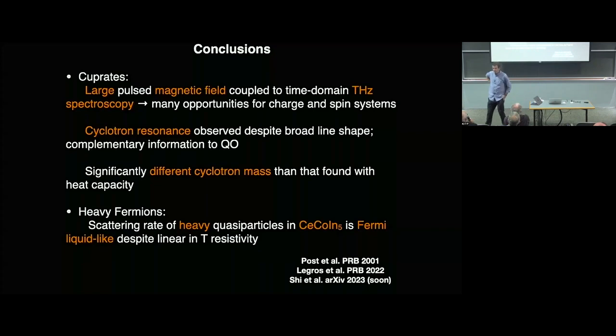One is that the behavior of the mass that you find, which increases with doping, is really intriguing and counterintuitive with respect to any picture related to strong correlations. On the other hand, the fact that you get an excess of M star from the specific heat in a range which is intermediate around P star, although it is rather broad, could perhaps be attributed to the fact that the specific heat could get some contribution from non-fermionic excitations, so from bosonic things. I have a comment on that, but go ahead.